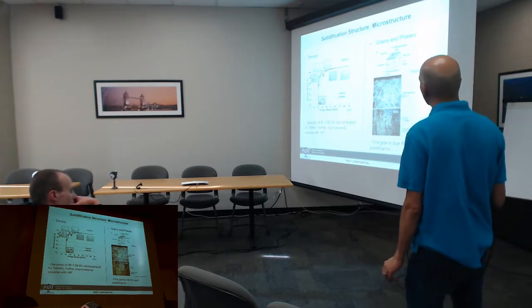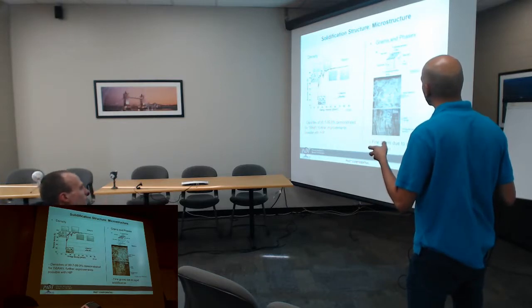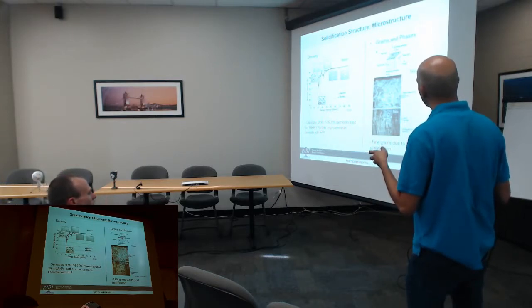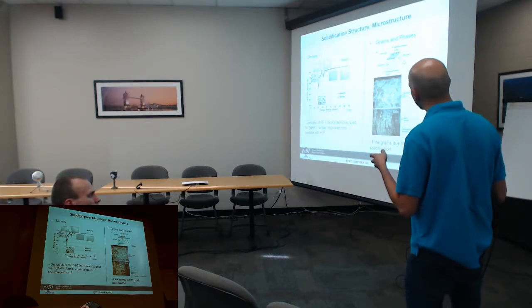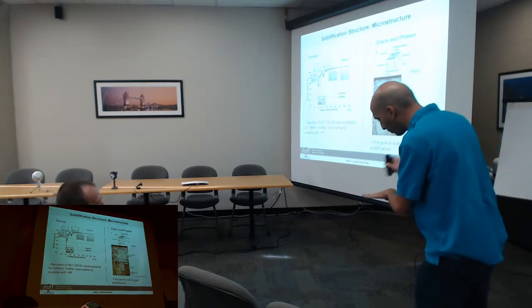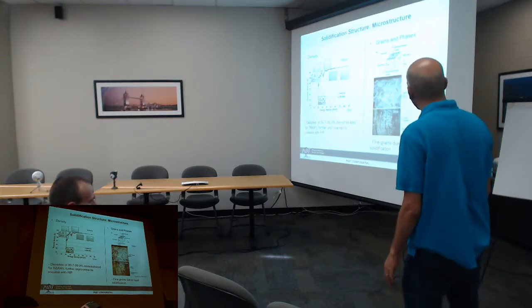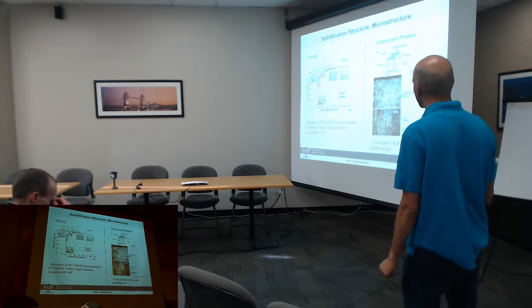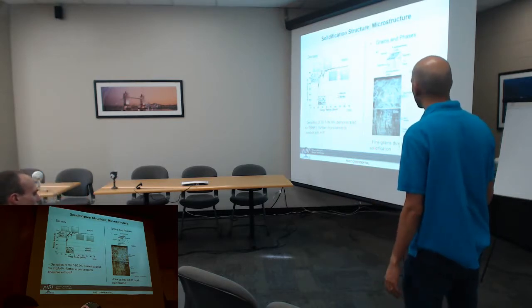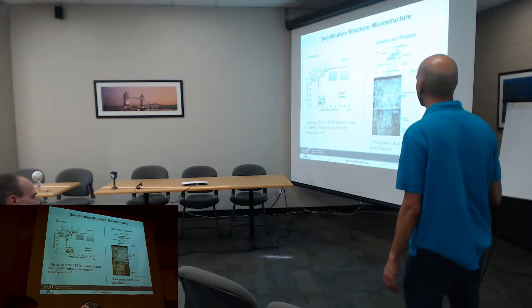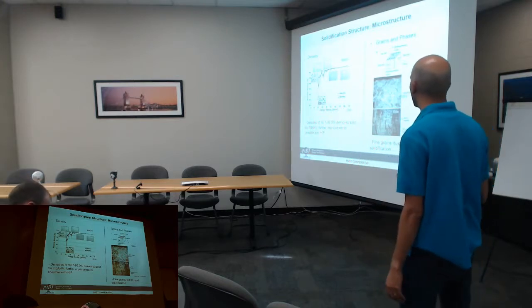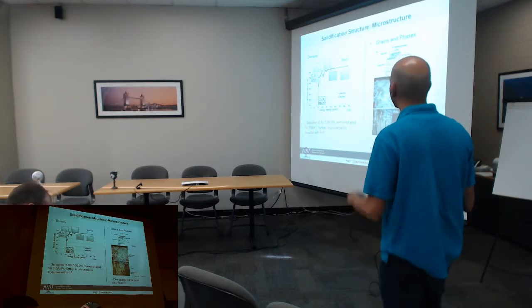The second thing I already mentioned is the solidification grain structure. There is some structure to this. So this is the top view where the laser beam is scanning like this, and this is about as wide as this. And in this image you can make out the separation when you're looking from the top and the laser is scanning. You pick that up. And if you look at it from the side and you cross-section it, some people have shown, again, for titanium 6-4 with a laser-based system, this kind of directionality to the grains and the way they appeared as bands if you took a cross-section. So that's just an observation.